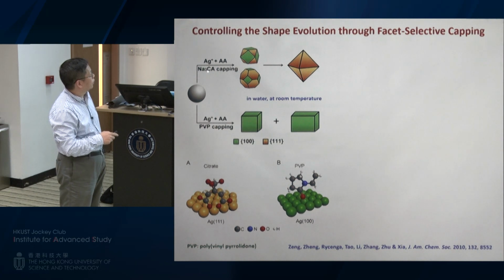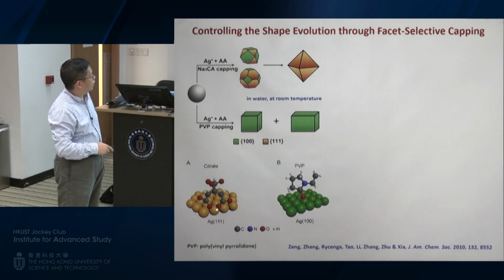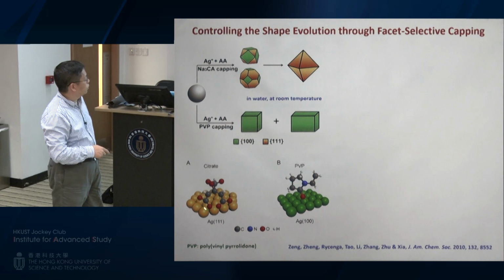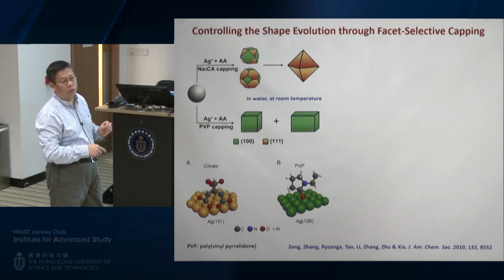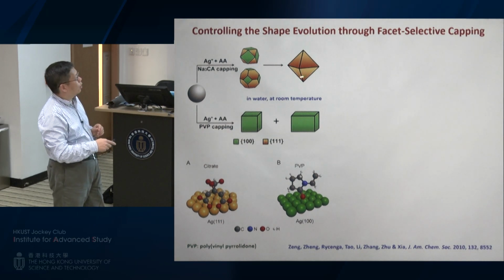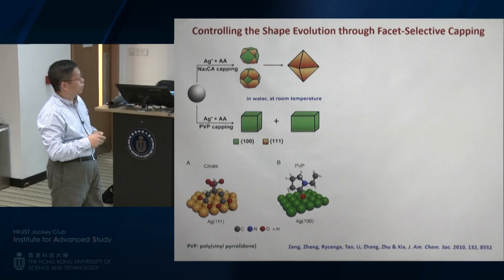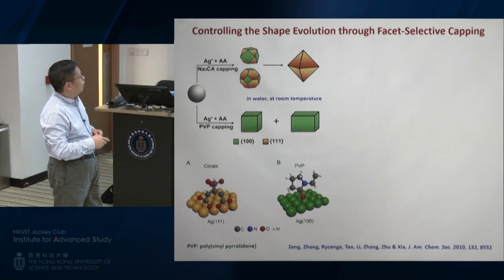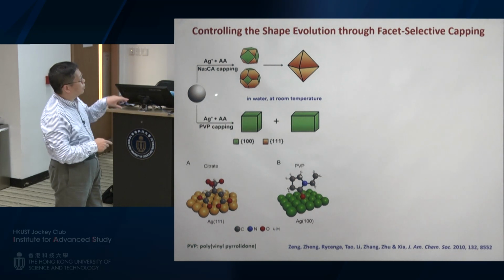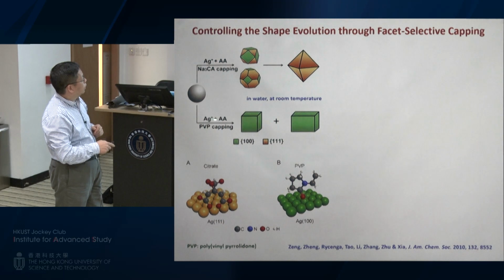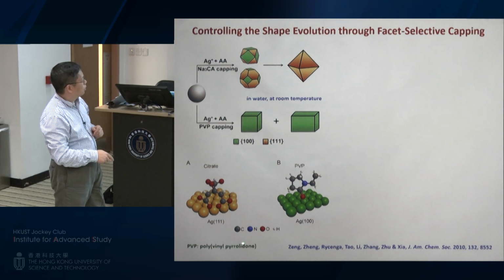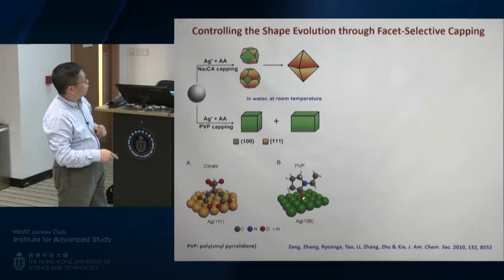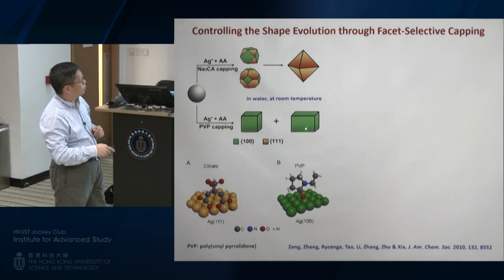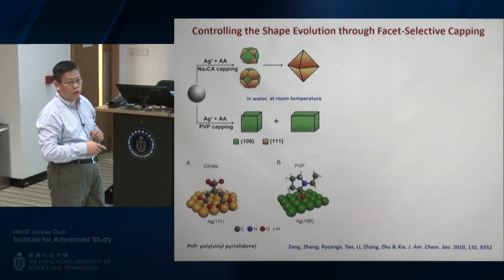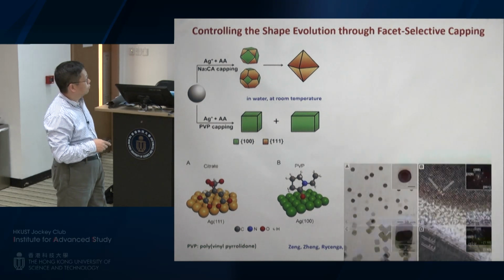In one synthesis, you can have sodium citrate. Sodium citrate actually will bind to silver 111 facet more strongly than 100. So that's why the final product is going to be enclosed in 111 facet. And in parallel, you can have a similar synthesis, almost identical except the capping agent. So you can use PVP, polyvinyl pyrrolidone actually. That will bind to 100 facet more strongly than 111. So the final product will be basically a cubic shape with 100 facet on the surface.